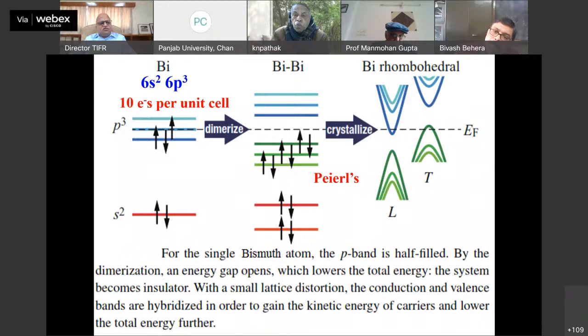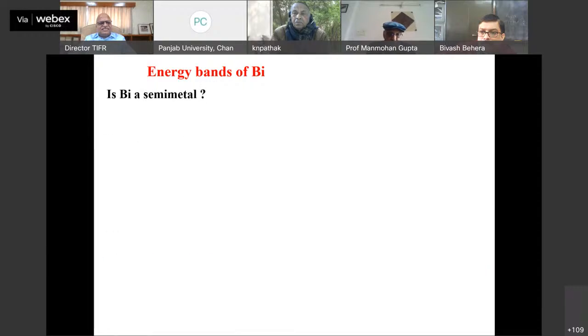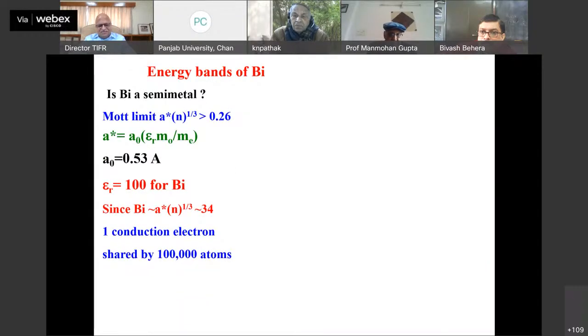When you bring two bismuth atoms together, they undergo dimerization. What you should have had is some sort of a Peierls transition, so that it should have been really an insulator. But nature doesn't do it that way. There is a Peierls distortion. So in the structure, instead of an FCC lattice, it goes into a rhombohedral structure, because that is the most energetically favorable thing. And it has this very unusual band structure. The top of the valence band is above the bottom of the conduction band. There is an overlap of the conduction band and the valence band, which I will come to later. So this is the stable configuration of rhombohedral bismuth, which has its unique band structure.